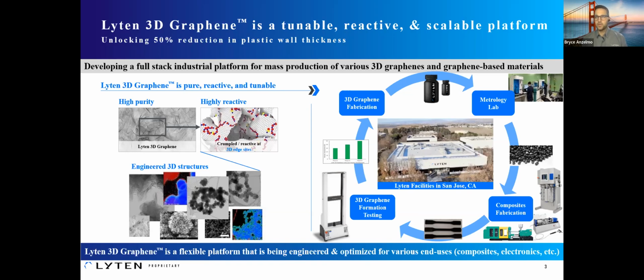And then what we do is once we're satisfied with that material spec, we then put that into the application. So you see here composites, relevant to the audience here. We have a small injection molder as well as a twin screw compounder. And then we have the ability actually with some of the IACMI partners, this consortium has been great actually for us, to scale up to, we would call that maybe a pilot scale. And then we rely on the industrial scale, at least on our partners, our commercial partners at the moment.